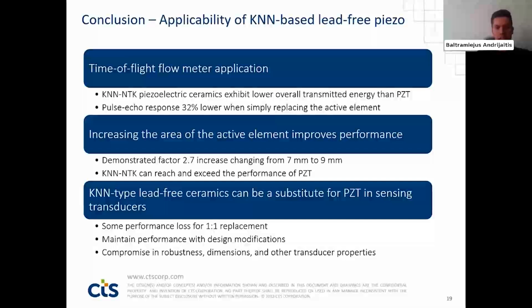However, increasing the active area by 29% increased effectiveness significantly by 2.7 times, which leads us to the final conclusion that lead-based materials could be substituted by lead-free materials, however, with implemented design modifications and compromise in robustness, dimensions, and other transducer properties.